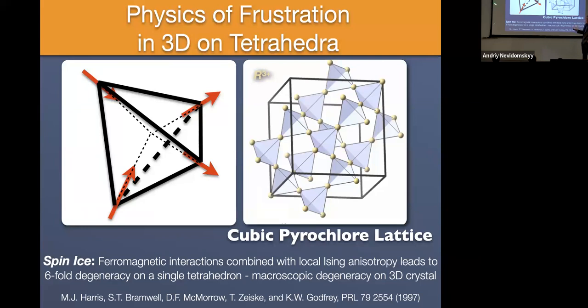So you could convince yourself pretty quickly that with that anisotropy and that interaction, the best you can do on any one tetrahedron is to arrange 2 of the spins pointing in and 2 of the spins pointing out, okay, as is drawn here. But you could also convince yourself pretty quickly that there are 6 different ways you can do that on a single tetrahedron, okay? And so there's a degeneracy of 6. So if you like, the magnetization could either point left to right, right to left, up, down, and in, out, if you like. And at any rate, you've got this degeneracy of 6 associated with one tetrahedron. And then if you connect the tetrahedra together to fill three-dimensional space, you get a degeneracy that's going to scale very quickly with the number of tetrahedra you connect together to start filling space.